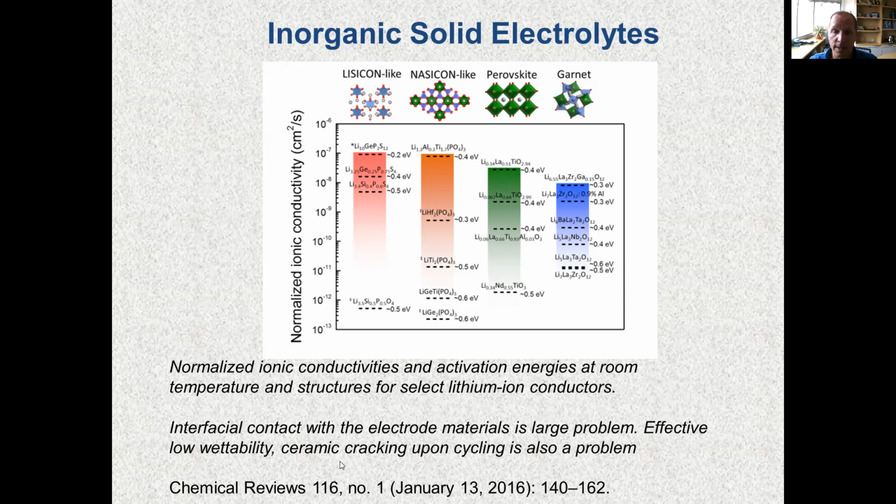However, when you go to an all solid state system where you have an all ceramic electrolyte, even these small 5 or 10% volumetric changes of the anode and the cathode during cycling can result in significant cracking of these materials. And this significant cracking results in significant impedance growth of the cathode or of the electrolyte itself, and even poorer contact between the solid ceramic electrolytes and the electrode materials. And so while there's certainly a lot of interest in going away from liquid electrolytes and going to full solid state systems, especially these solid ceramic electrolytes, there are real large challenges in terms of building real commercial cells with these solid electrolytes.